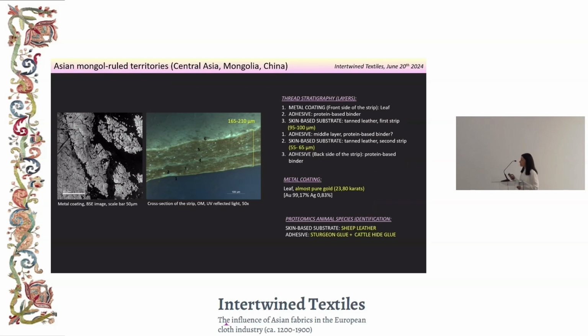Microanalysis revealed that the metal coating was made of almost pure gold. For the stratigraphy of the sample, we took the sample, embedded it in resin, and under a UV light, we observed the cross-section of the thread. You can see the different layers that make up the thread, a very complex structure. You can see in layer 1 the metal coating, and then we have found in all this category of threads an adhesive layer used both on the back of the strip as well as to join the metal to the skin. In this particular case, 2 strips of skin have been coupled together with a middle layer of adhesive, probably to get a thicker strip.